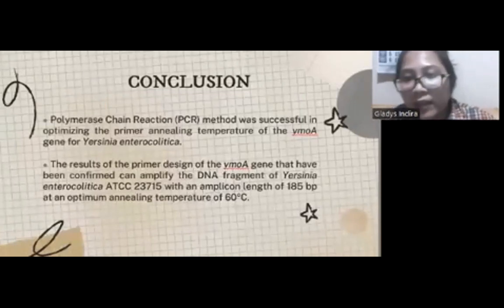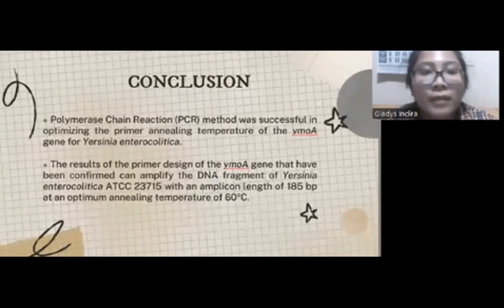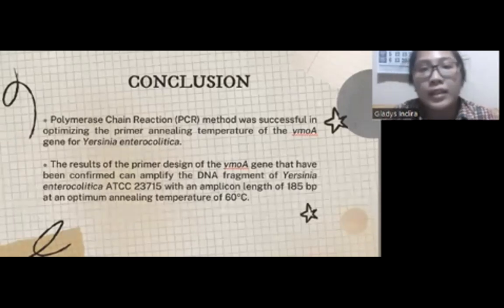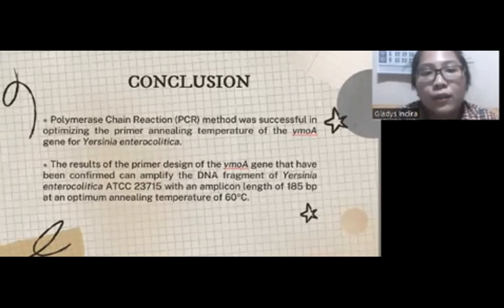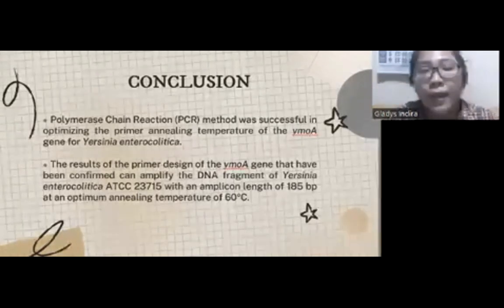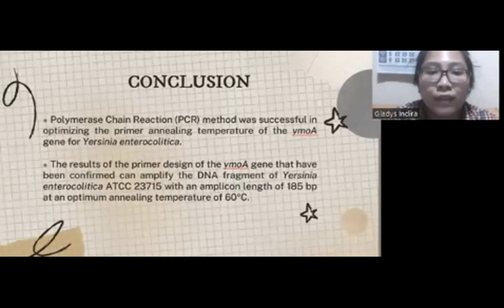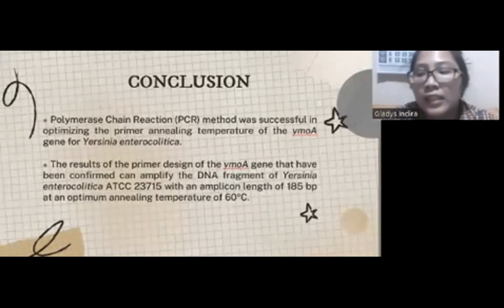The conclusions that we obtain from this research: first, the polymerase chain reaction or PCR method was successful in optimizing the primer annealing temperature of the YmoA gene for Yersinia enterocolitica. And then the primer design of the YmoA gene has been confirmed to amplify the DNA fragment of Yersinia enterocolitica ATCC 23715 with an amplicon length of 185 base pairs at an optimum annealing temperature of 60 degrees Celsius.